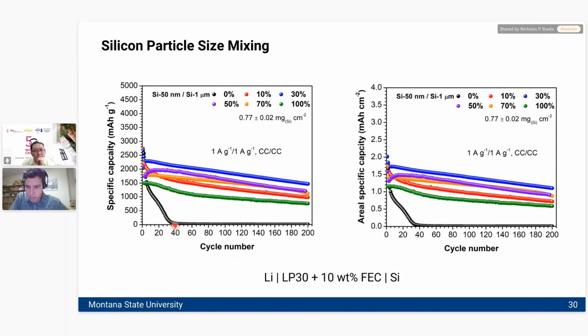Again, it pretty much dies before cycle 40. This is a pretty representative case for not having any nano particles at all. And as soon as Wei added just a little bit of the nanoparticle system, here we have the 10% mixture. So this is 10% nanoparticles, 90% micron particles. You got a massive improvement. When he added 30%, it went up to this blue line.